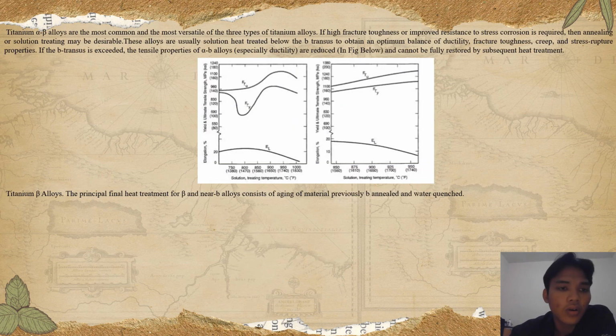Titanium alpha-beta alloys are the most common and the most versatile of the three types of titanium alloys. If high fracture toughness or improved resistance to stress corrosion is required, then annealing or solution treating may be desirable. The alloys are usually solution treated below the beta transus to obtain an optimum balance of ductility, fracture toughness, creep, and stress rupture properties. If the beta transus is exceeded, the tensile properties of alpha-beta alloys, especially the ductility, are reduced in the picture below and cannot be fully restored by subsequent heat treatment.